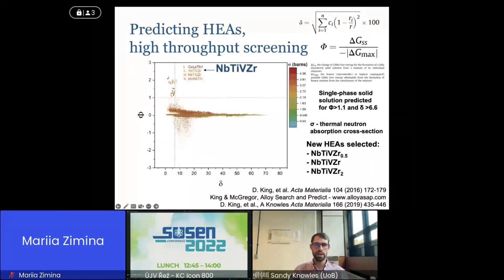This was actually a data library approach, looking at atomic size misfit as well as your propensity to form a solid solution, so your Gibbs free energy of mixing versus intermetallic formation. So we have these 2 parameters: not very large atomic size misfit, as well as a low driving force for intermetallic production. And the nice thing with this approach, where the code is publicly available, is we could screen, in this case, 100,000 compositions, and we've subsequently done another study where we've done over 1 million high entropy compositions.